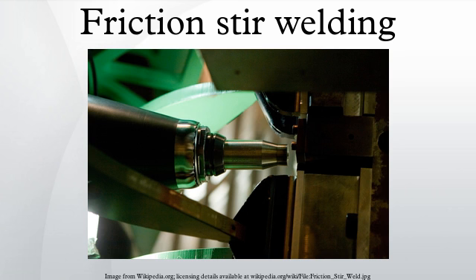If the material is too cold, then voids or other flaws may be present in the stir zone and in extreme cases the tool may break. Excessively high heat input, on the other hand, may be detrimental to the final properties of the weld. Theoretically, this could even result in defects due to the liquation of low melting point phases. These competing demands lead on to the concept of a processing window, the range of processing parameters, viz. tool rotation and traverse speed, that will produce a good quality weld. Within this window, the resulting weld will have a sufficiently high heat input to ensure adequate material plasticity, but not so high that the weld properties are excessively deteriorated.